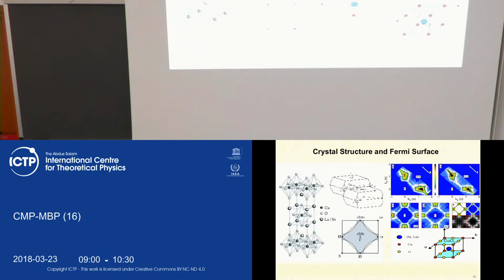If you calculate a certain response function with such a Fermi surface, for example the Lindhard function, the very same way as we did it for the spherical Fermi surface, you will find that the polarization operator, which is the density-density correlation function, or the spin susceptibility, which is the spin-spin correlation function, is logarithmically divergent, where the logarithm contains the upper cutoff, which is the Fermi energy, and the low cutoff, which is a deviation from half filling, or temperature, or anything else. So you will get a divergent logarithm, which then immediately implies the existence of strong correlations.